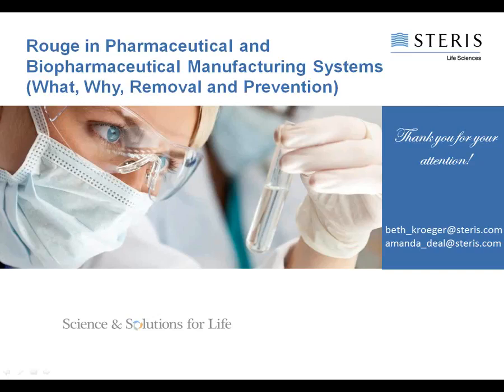Did you want to add to that? Yeah, there are different methodologies. Like you said, if it's a new piece of equipment, that's a little bit different. If you're trying to remove those cutting oils or lubricants, then I would just recommend a general cleaning. But if it's an actual process soil, you can do coupon studies to determine what is actually clean by looking at visibly clean, water break free, and gravimetric analysis of that, or even take it up to HPLC or TOC, just like you would a normal process soil.